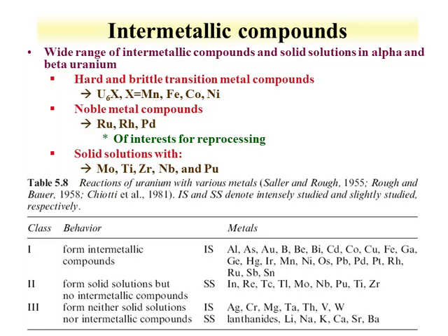So that intermetallic has specific stoichiometries, and these compounds will form. So if you had uranium metal against stainless steel, which can occur in a fast reactor, and you started to have diffusion of the stainless steel into the uranium, you would change that uranium metal to this intermetallic compound. Noble metals can also form compounds with uranium, these intermetallic compounds. And then as we discussed with the alloys, we get something that looks more like solid solutions.